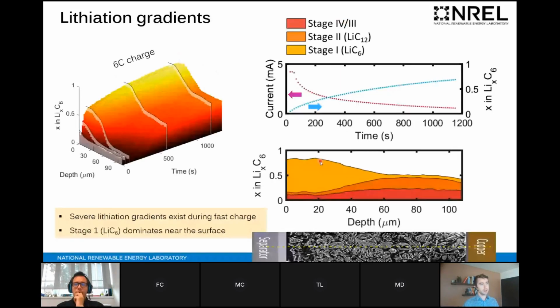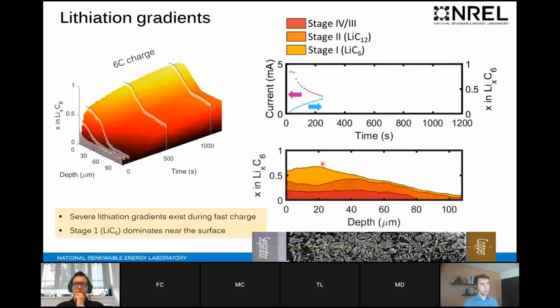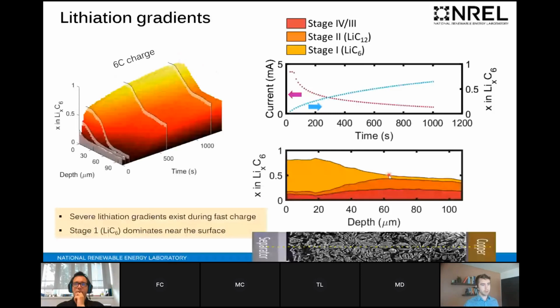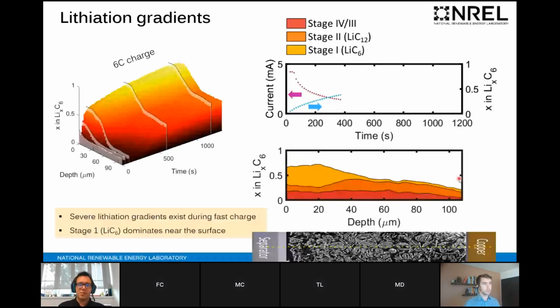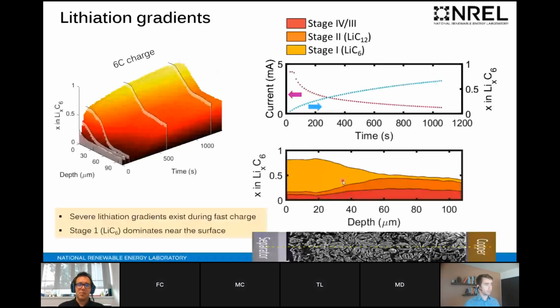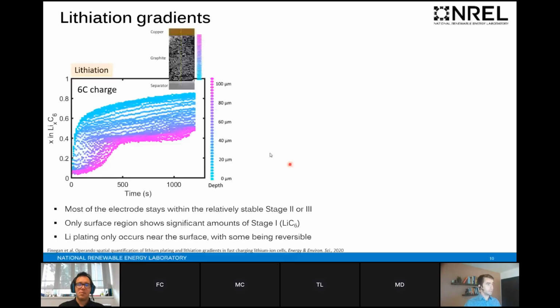So you can see close to the separator, to about 40 micrometers in depth, we get a lot of stage 1, so full lithiation, whereas in the rest of the electrode there's very little stage 1, and most of the electrode consists of stage 3 or stage 2. So you can already see very severe lithiation gradients in this electrode. And this data was plotted here on a static plot. It's a bit easier to look at.